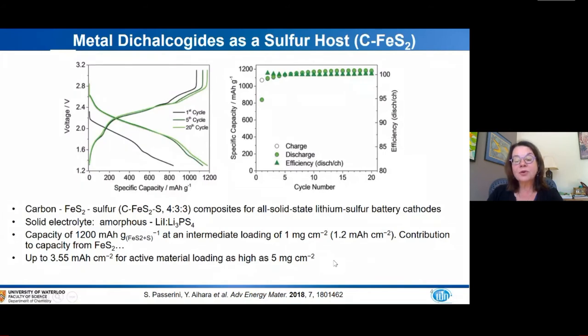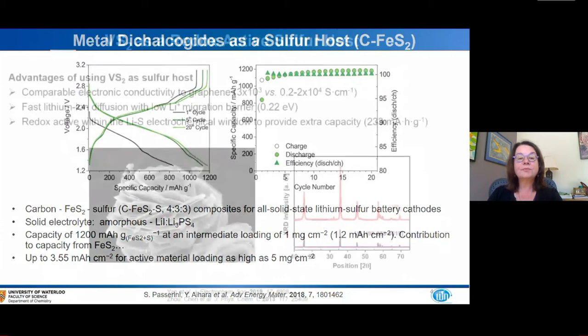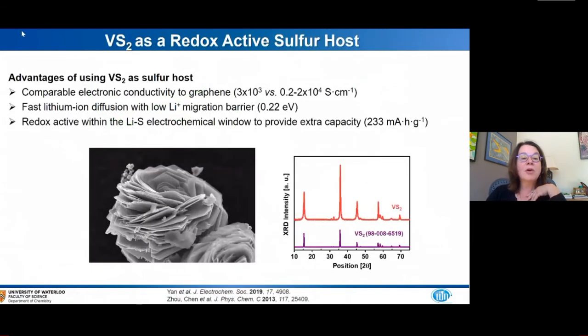So we decided to try a different tactic, which is to use a metallic disulfide, and our material of choice was vanadium disulfide. It has comparable electronic conductivity to graphene, on the order of 3,000 Siemens per centimeter, so it's really truly metallic. It also exhibits fast ion diffusion with a low migration energy barrier of about 0.22 volts.